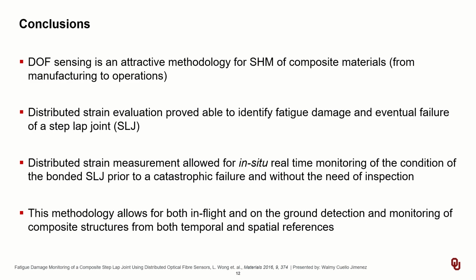Conclusions: distributed optical fiber sensing is an attractive methodology for structural monitoring of composite material. Distributed strain evaluation proved able to identify fatigue damage and eventual failure of a step lap joint. Distributed strain measurements allow for in situ real-time monitoring of the condition of the bonded step lap joint prior to a catastrophic failure taking place, and of course without the need of any inspection.